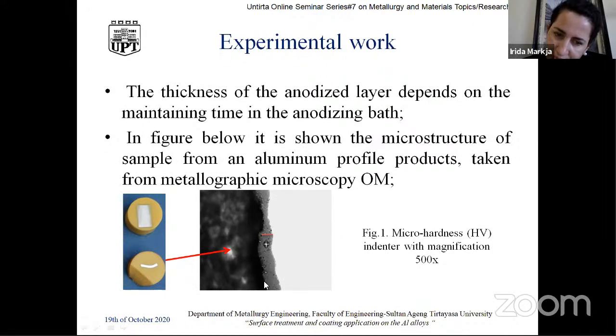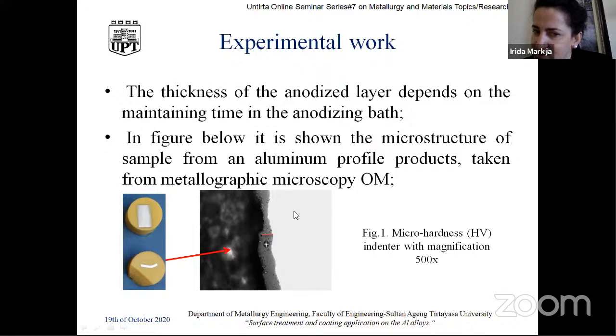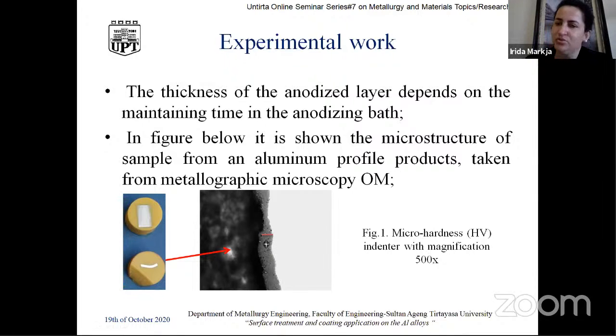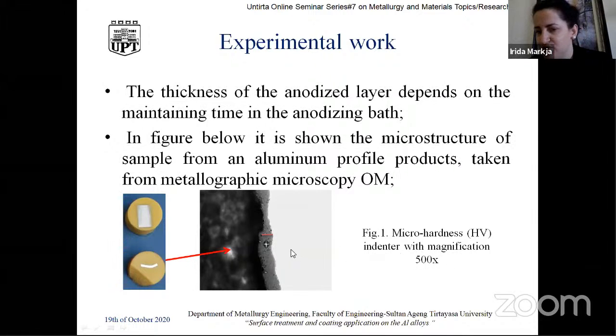And this is the whole oxide layer created on the material. And this is the profile of the aluminum product without treatments. This is the new surface created from the anodizing process, where we will see that the thickness is not the same throughout this microstructure that we have taken at the moment with one indentation. So in all the elongation, all the parts of the layers, we will make different indentations to see the micro hardness and to evaluate or measure the mechanical properties of the samples or of the layer. The magnification for this microstructure was 500.